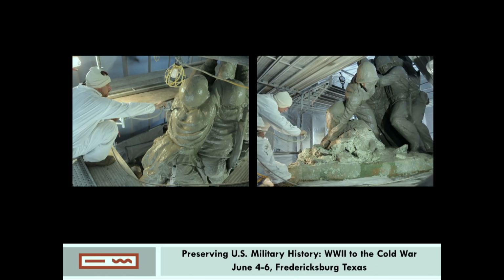I included those details in the paper as well, but the sequence was one coat of Keim Concretal. The surface was then de-limed. Two flood coats of Keim Silane 100 water repellent were applied, and then one base coat of their product, which is called Soldalit, was applied by airless sprayer. That's what you see going on here.